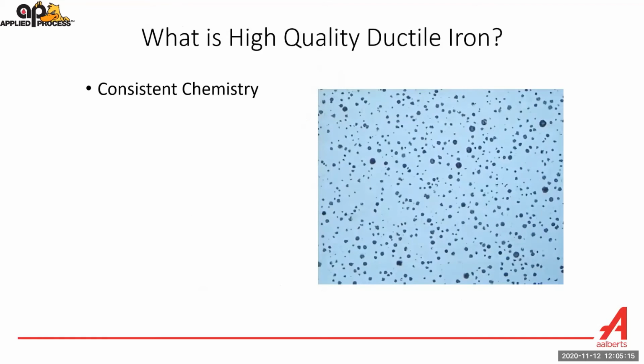And just some guidelines on that. It has to have consistent chemistry, just like with steel. If you buy ductile iron with consistent chemistry, you will get good results. And you also want, you see these, the black dots. This is a photomicrograph taken at 100x. Those are the graphite nodules that appear during solidification. And we want lots of those nodules. So we want a minimum of 100 of these little graphite nodules in a square millimeter.